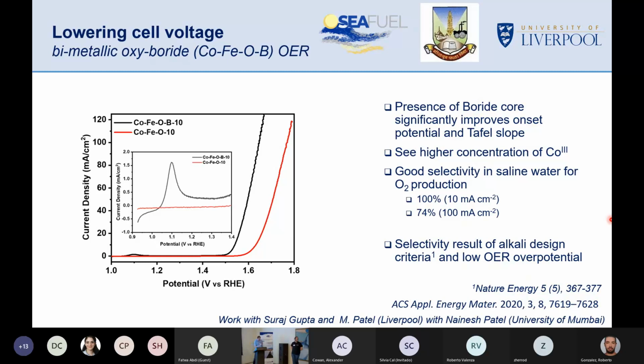So, yeah, these borides are really interesting because you make the transition metal boride and then you put it into your electrolyte, and they'll basically form a sort of porous oxide type structure on the surface. So at low pH, these will just dissolve away. So they don't work at low pH.